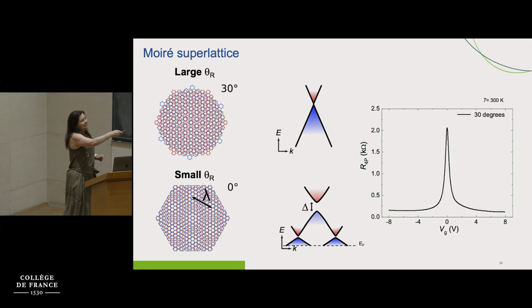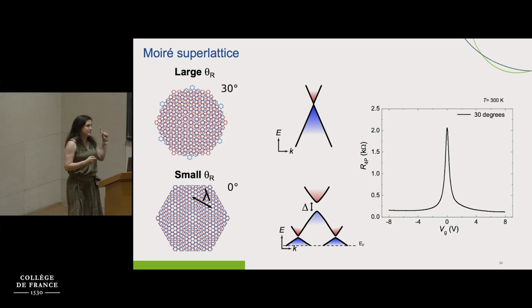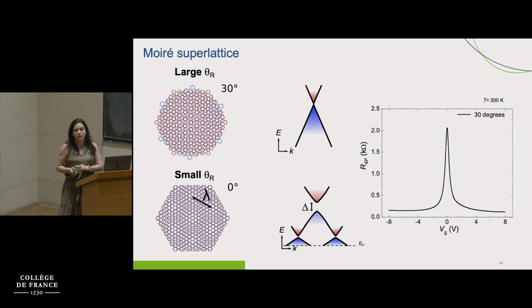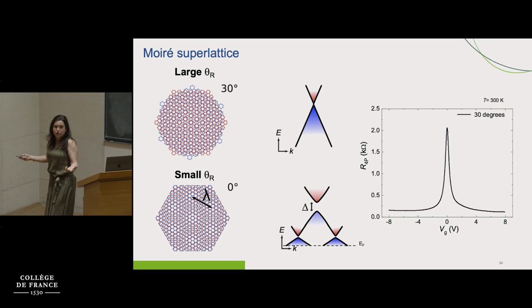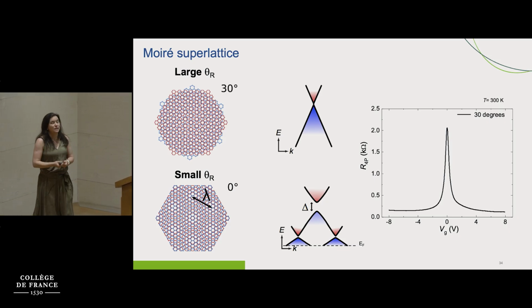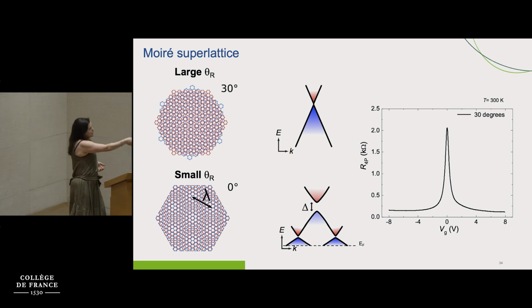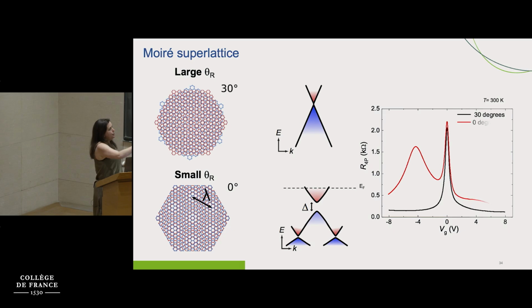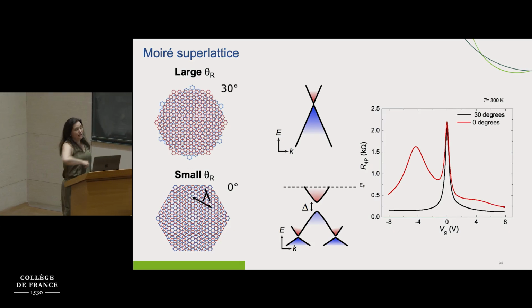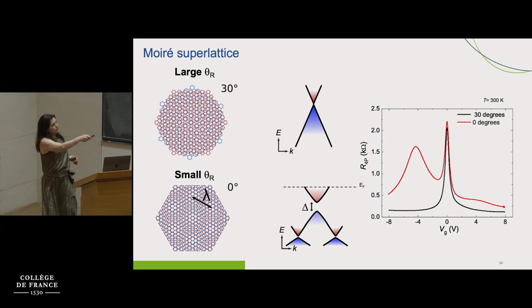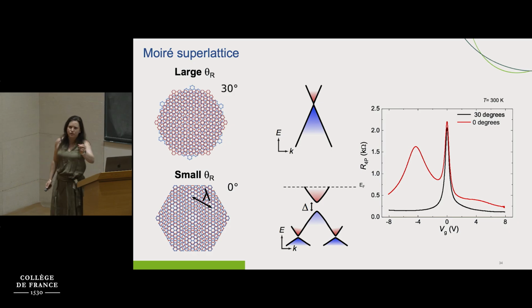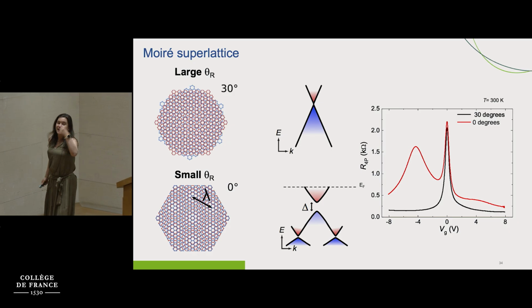In particular, the central energy gap, the one at the charge neutrality point, has two origins. The first one is because I'm breaking inversion symmetry in my system, and the second one is because of the strain that is developed in the commensurate state. So now, if I measure transport there, I'm going to see a new feature. I'm going to see this peak that shows up. Please keep in mind that these are measurements at room temperature, which also means that this modification is strong enough that I can see it even at room temperature.